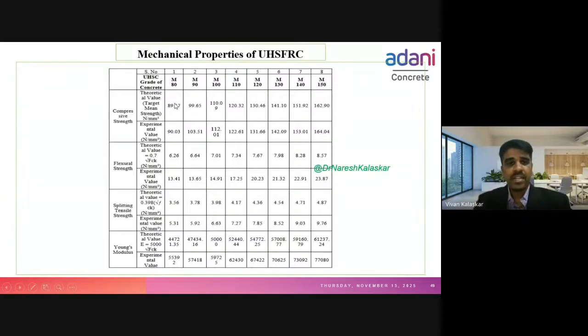Compressive strength: the top row is the target mean strength, and below is the experimental result. We got the target mean strength of 162 MPa for M150, and we got 164 MPa compressive strength. Flexural strength, we got 23.87 against 8.57 as per code. Splitting tensile strength as per code for M150 is 4.87, and we got 9.76. And Young's modulus for M150 should be 61,237.24, but we got 77,080.